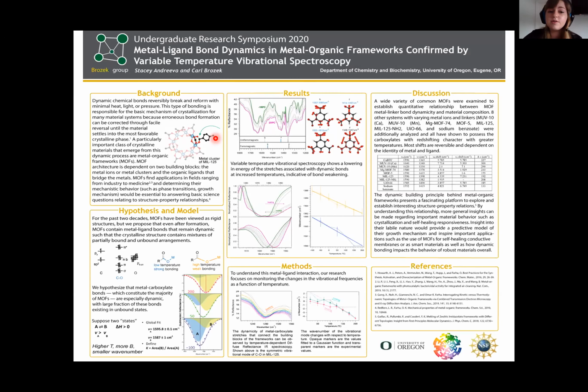And we observed that it is more labile than it was previously believed, and was the origin for other studies as well. And we derived this inspiration from other studies that describe the fascinating phenomena of MOFs that undergo post-synthetic modification like cation or ligand exchange, as well as phonon softening, induced phase transitions, and sometimes even electronic transitions, and temperature-induced metal-ligand decomplexation in self-healing polymers, which was explored by Raman vibrational spectroscopy. Also, molecular dynamic simulations showed the dynamic association and dissociation process between carboxylate and the metal.